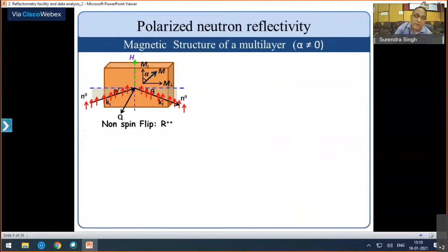Now another case, where we have magnetizations in the magnetic sample which is not aligned along the applied field. So the applied field will have now m parallel and m perpendicular components. Please remember, this m parallel and perpendicular component we are saying is in the plane - as I said earlier, out of plane we cannot say anything. We have two components, and as you know, for any spin particle, if you apply a magnetic field perpendicular to the spin direction or at any angle...